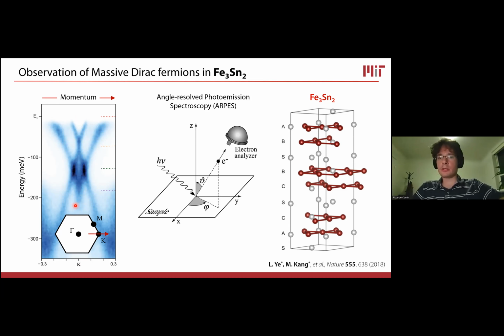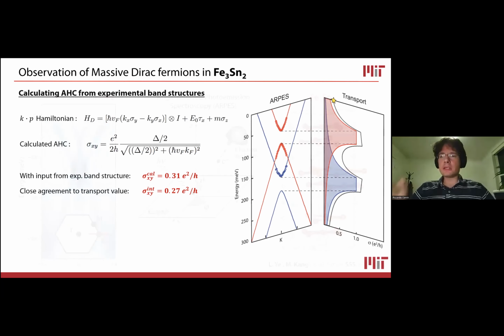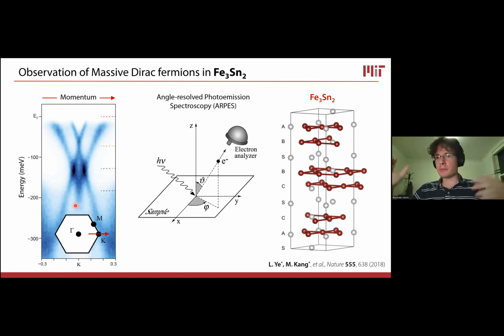And so this is happening because of some hybridization between the Kagome bilayers. They face each other, so they hybridize and they form something that you can think of essentially as a bonding anti-bonding splitting. So one of these bands is the bonding band, the other one is the anti-bonding band. It's very simple hybridization physics.